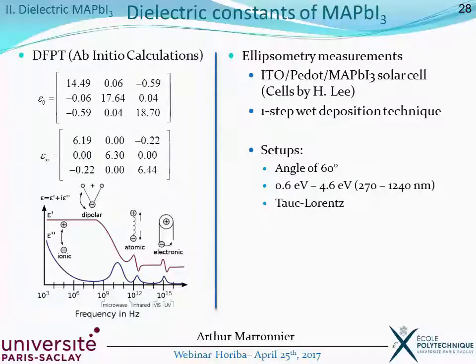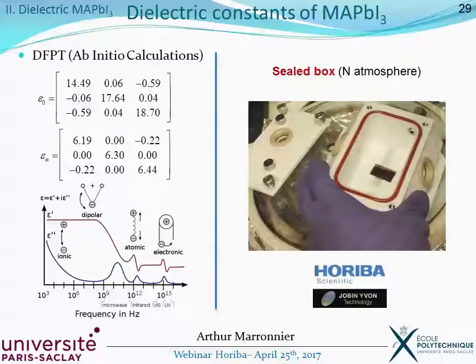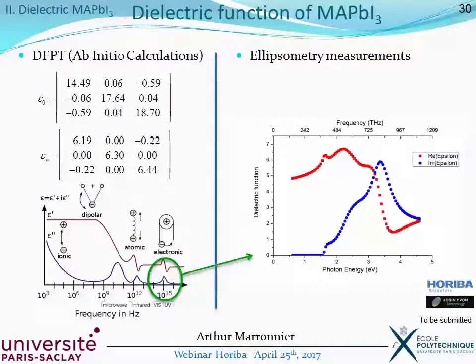And as for the ellipsometry machine, we've used an angle of 60 degrees, this range of energies, and to obtain the optical constants, we've used a Tauc-Lorentz modeling. Remember that perovskites are unstable, and this is why we've used a seal box provided by HORIBA in order to keep the perovskite cells in a nitrogen atmosphere, which is actually the nitrogen atmosphere with which they were made, in the glove box. So here are the results from our ellipsometry measurements in the visible range.